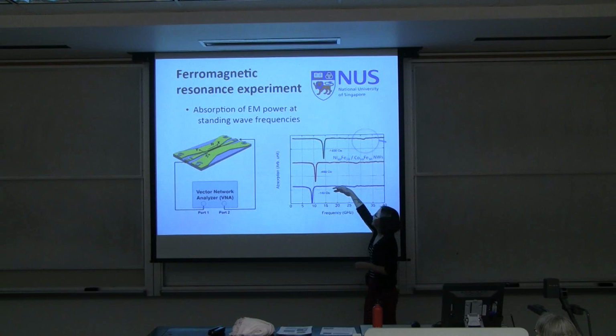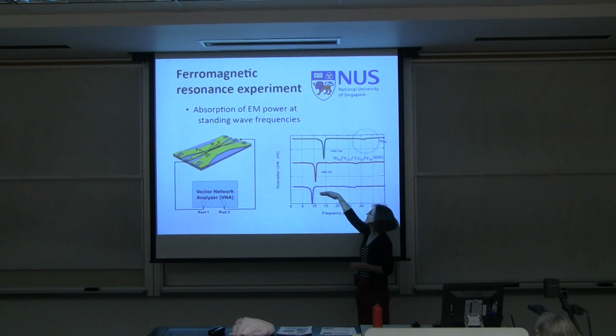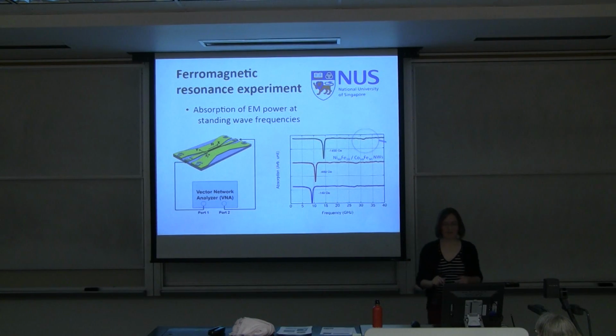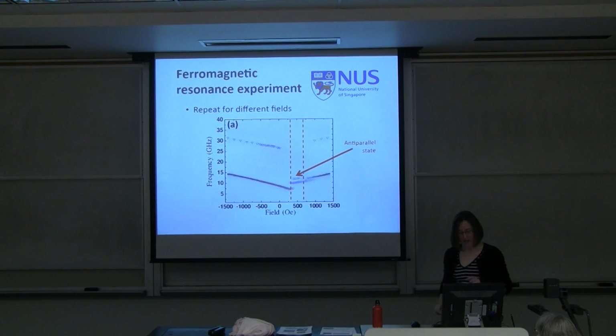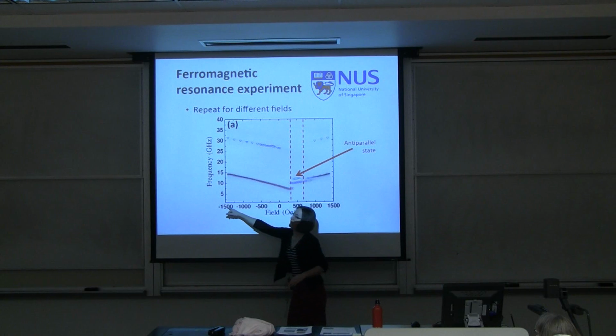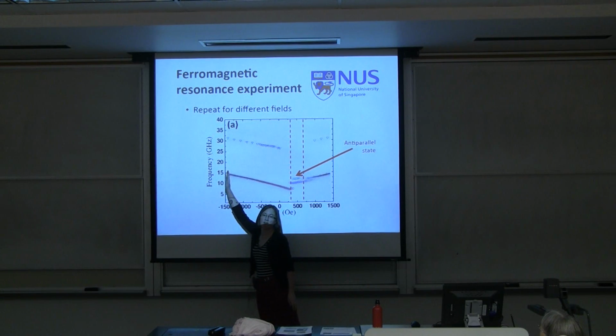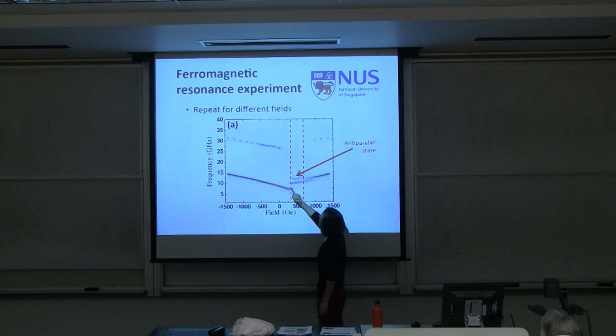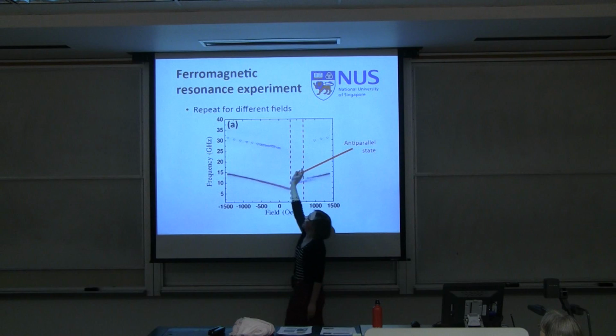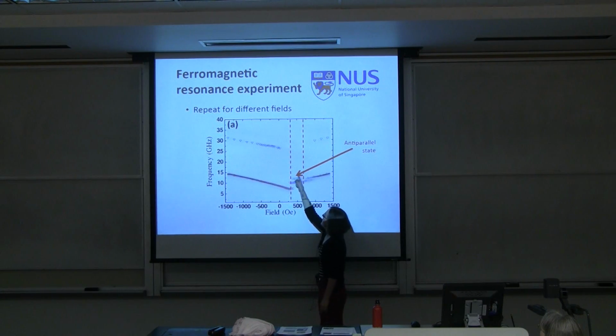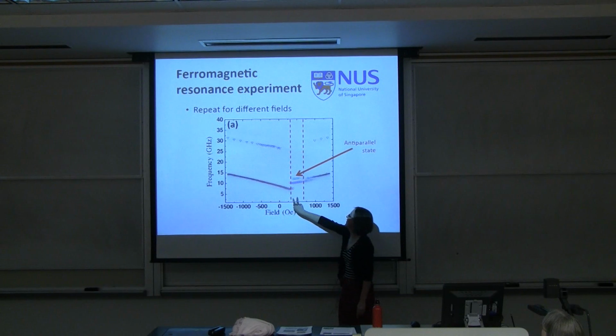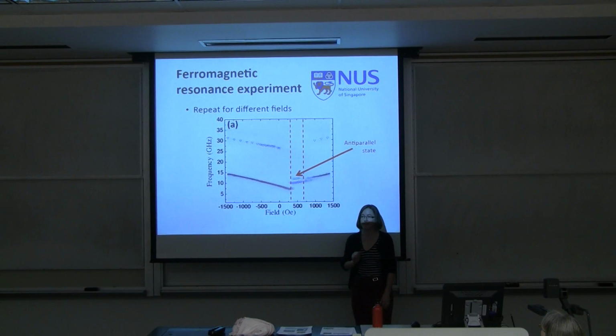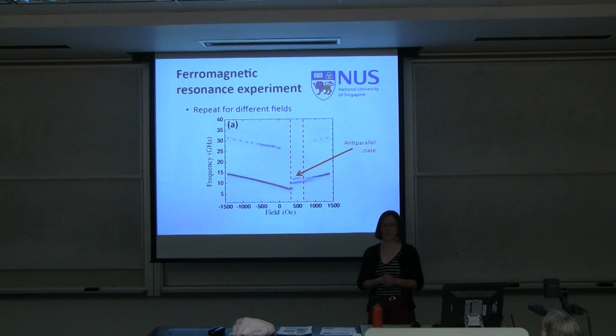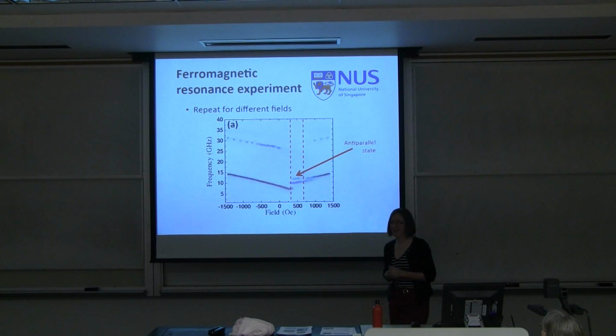Okay? So we can repeat this experiment over and over again for different static applied fields. And that's exactly what my colleagues in Singapore did. And so this is basically all the different fields they measured and the resonant frequencies they got out. So you can see there's our lowest frequency spin wave, and then up higher there's a higher frequency spin wave. And then in here there's something interesting going on, which is exactly the fields where our anti-parallel state was. Okay? So when the anti-parallel state exists, we have something different going on with the spin wave structure. All right, any questions on this?